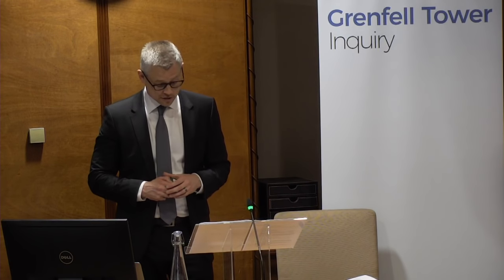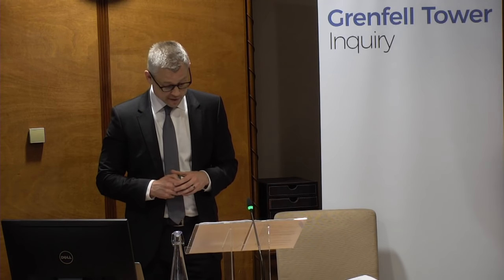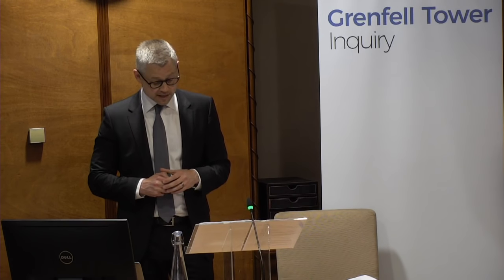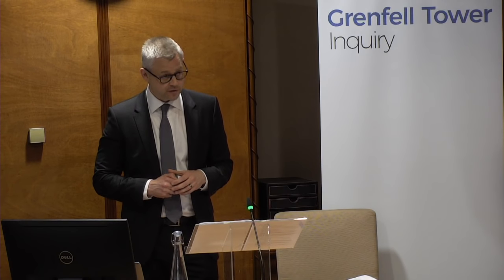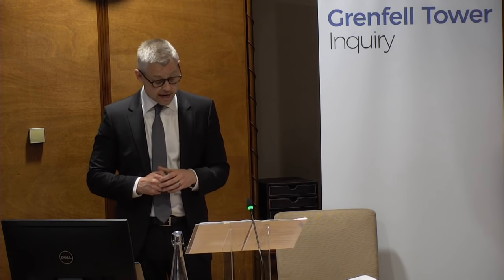A further special case of opposed flow flame spread is horizontal or lateral flame spread. This is similar to downward flame spread, and my next video shows the flame spreading from right to left. In this case, the rising hot gas draws air into the flame from left to right, hence referring to this as opposed flow flame spread, as in the case of downward flame spread. The heat transfer from the flame to the match is higher than in the downward case, as evidenced by the spread of the flame horizontally along the match.